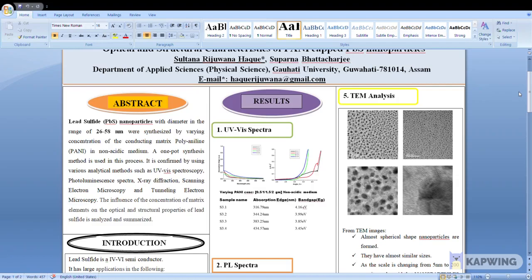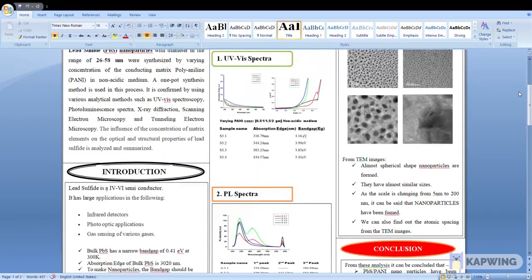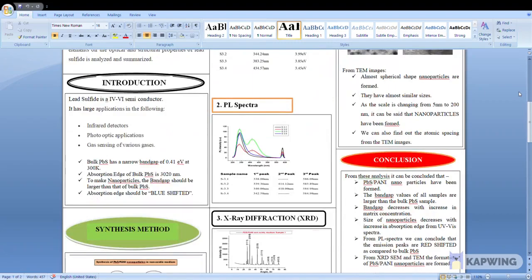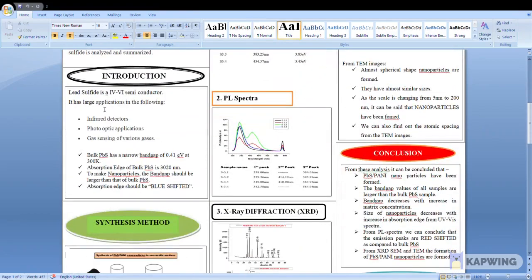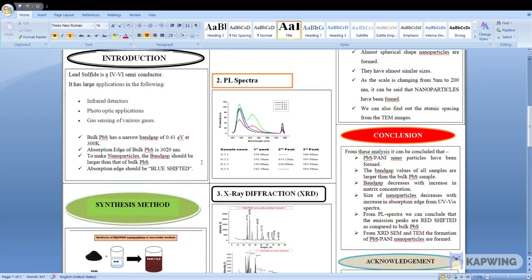Lead sulfide is a IV-VI semiconductor. It has various applications in infrared detectors, photo-optic applications, and gas sensing of various gases. Generally, the bulk lead sulfide has a narrow band gap of 0.41 electron volt and its absorption edge is 3020 nanometer. So, to make nanoparticles, the band gap should be larger than that of the bulk lead sulfide. The absorption edge should also be blue shifted.